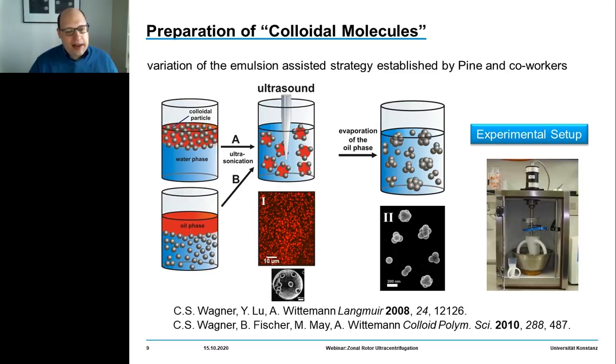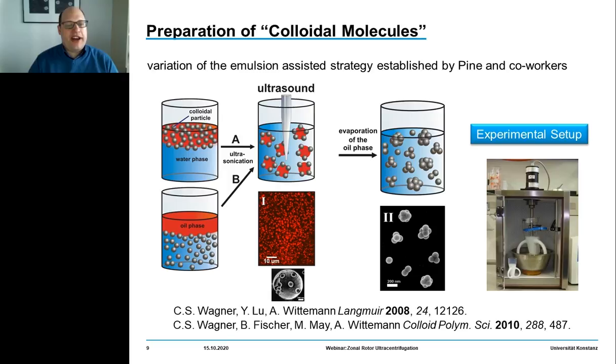The ultrasound helps us to control the size and dispersity of the emulsion droplets. If we have a closer look at such an emulsion droplet, we can see that the particles are indeed trapped at the surface, mediated by minimization of surface energy — a phenomenon referred to as the Pickering effect.